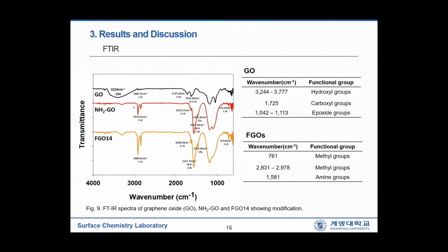This is a series of FTIR spectra taken for the graphene oxide, functionalized graphene oxide, and aminized graphene oxide. As you can see in the spectrum of GO, absorption peaks of hydroxyl groups appear in the range of 3244 to 3777 wave numbers, and the absorption peak of the carboxyl group appears at 1725 wave numbers. We can also see absorption peaks of the epoxide group in the range of 1042 to 1113 wave numbers.